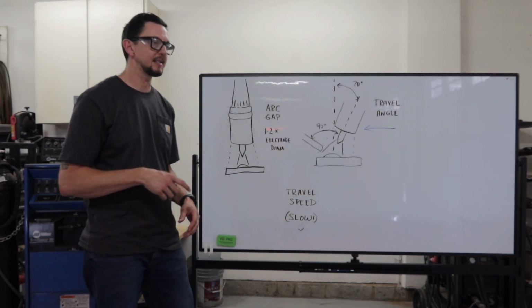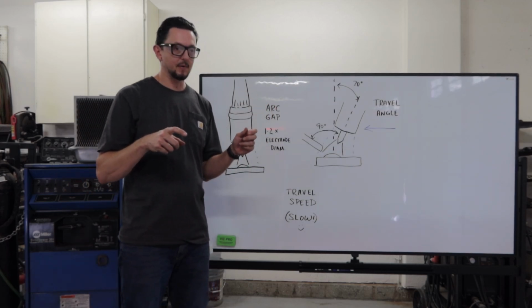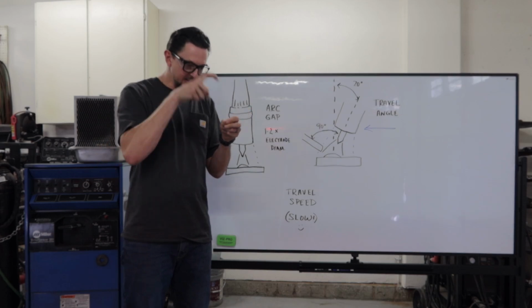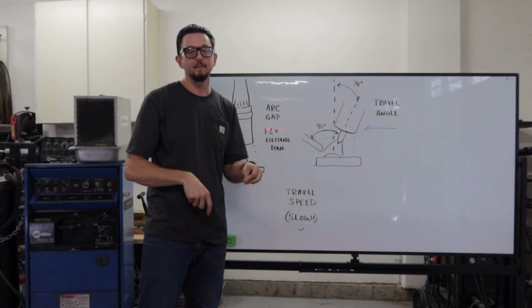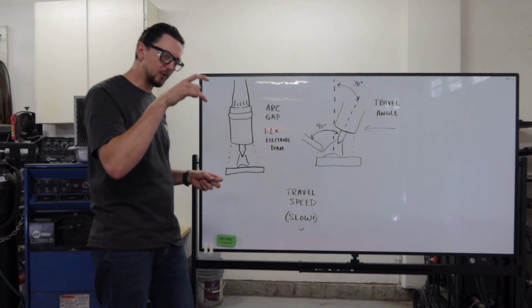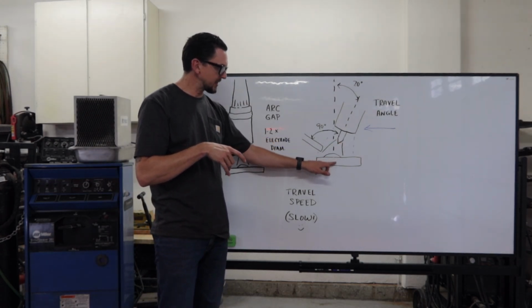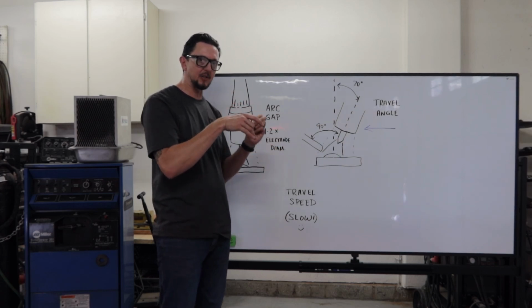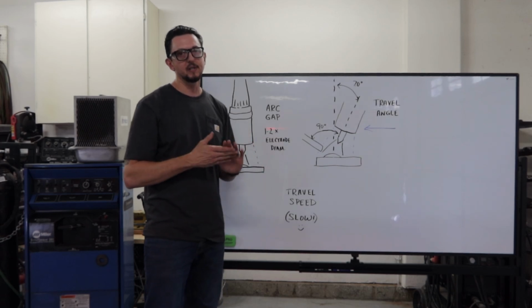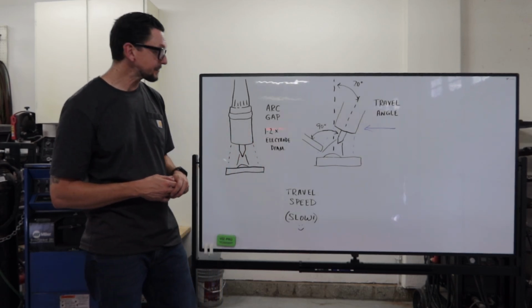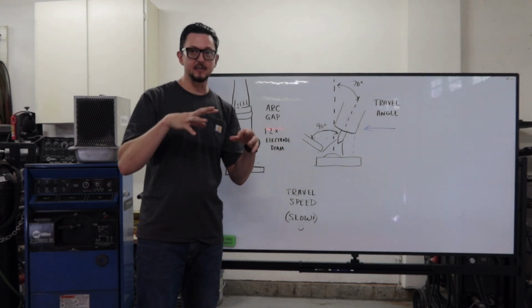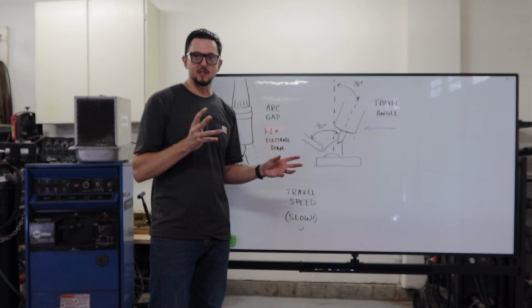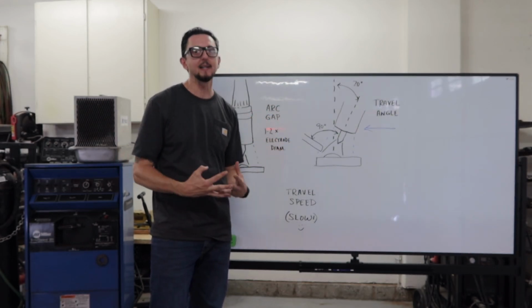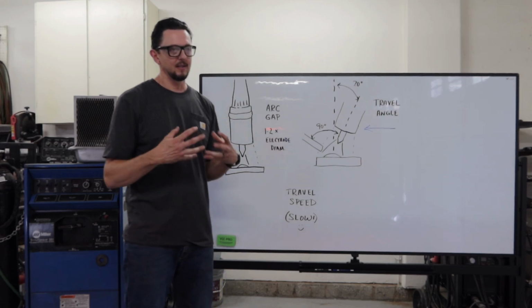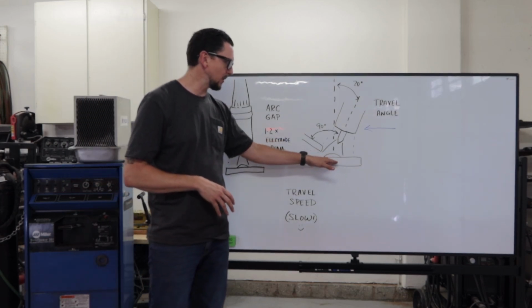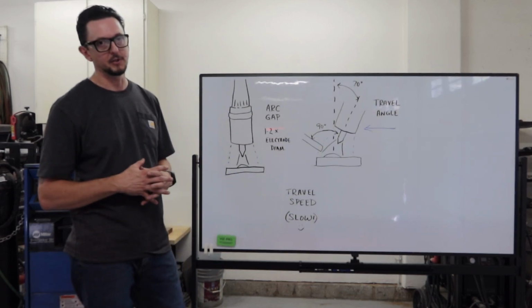And why I'm stressing this is that I see a lot of welders, when they first start off with TIG, take the filler metal and the torch and start trying to melt the filler metal onto the plate. Okay, that's not what we're doing with TIG welding. We are creating a weld pool with the torch. Once we get a weld pool started, then we are adding the filler metal to the weld pool. The weld pool is what melts the filler metal, okay? Otherwise, you're just melting metal on top of metal, and it's just a mess, and it doesn't really coalesce those two materials together. You have to start the weld pool with the torch first, then add the filler metal to it.